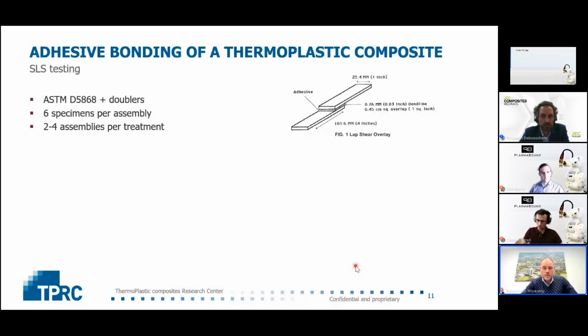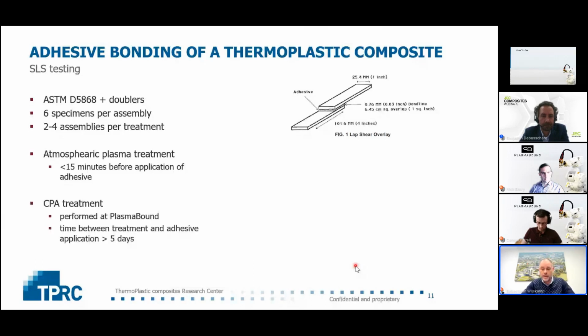And we cut 6 specimens out of each assembly, and we used between 2 to 4 assemblies per treatment. Well, the atmospheric plasma treatment was done very shortly before application of the adhesive, say less than 15 minutes, because we know that the plasma treatment decays over time. And we sent plates to Ireland, where Plasmabound performed the CPA, and then they nicely wrapped up the laminates and sent them back. So you could say that time between treatment and application of the film adhesive was longer than 5 days, so between 5 and 10 days.